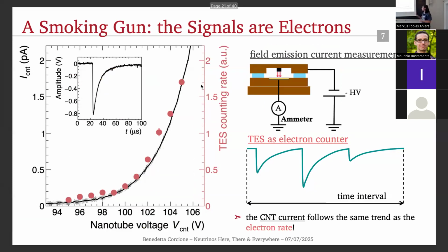Okay, so once all this setup was completed, we applied a certain potential to the nanotubes, and we started seeing signals on the TES. Now, here is a comparison between the field emission current of the sample of nanotubes and the signal rate we saw on the device. The black solid line is the field emission current, which was obtained simply by connecting a picoammeter in series with the TES and measuring the current. The TES counting rate is the red points, obtained simply by counting how many signals were detected in a precise time interval. And as you can see, these two different methods of measuring electrons give us the same exponential trend, which is the smoking gun confirming that the signals we were seeing were actually due to these electrons.